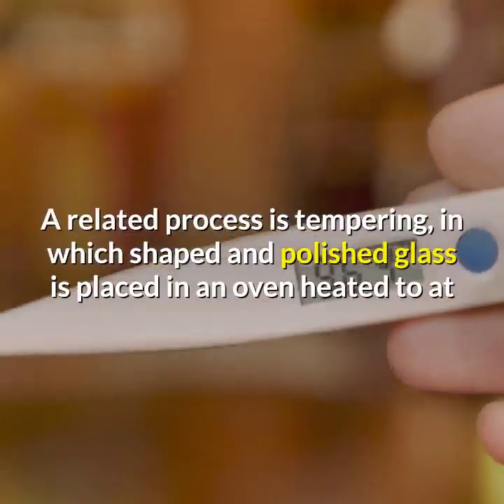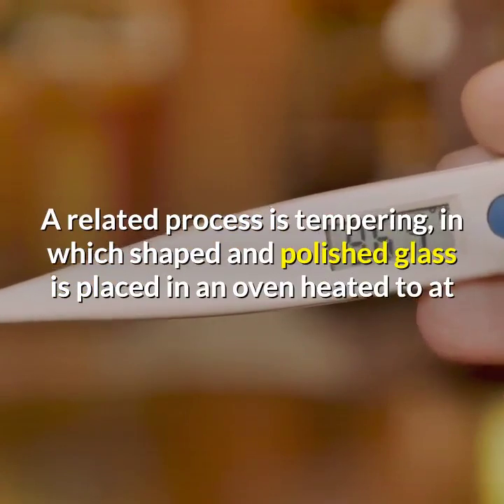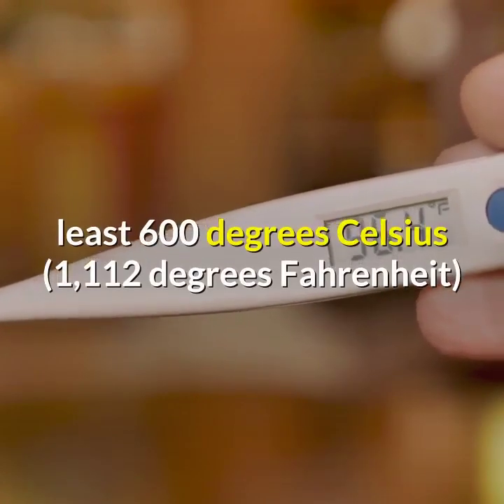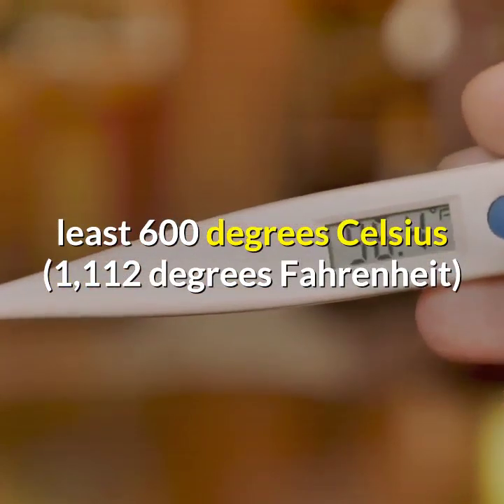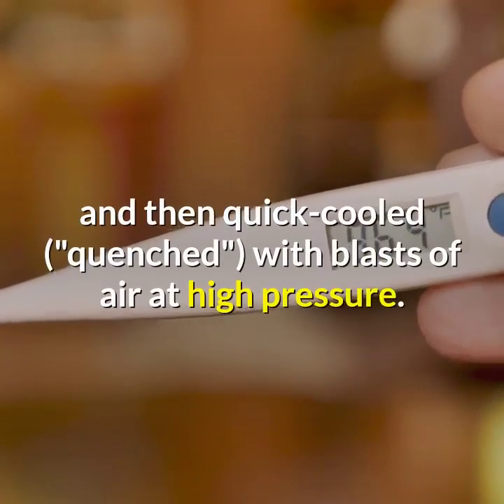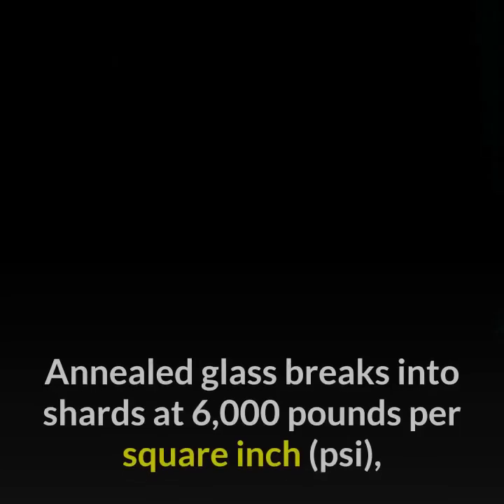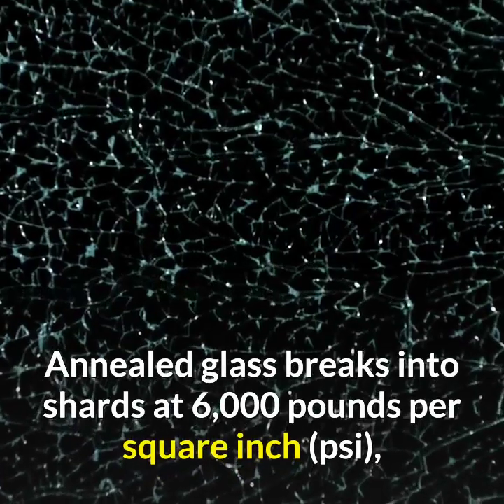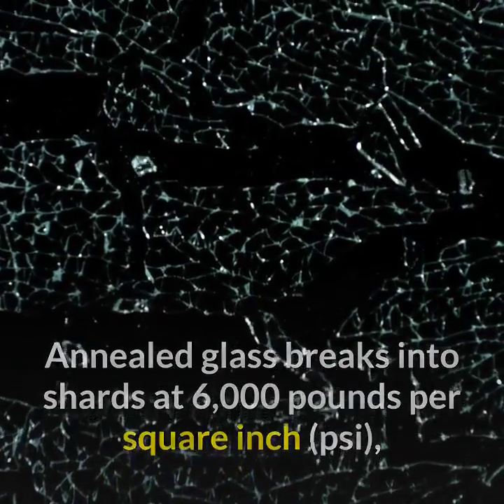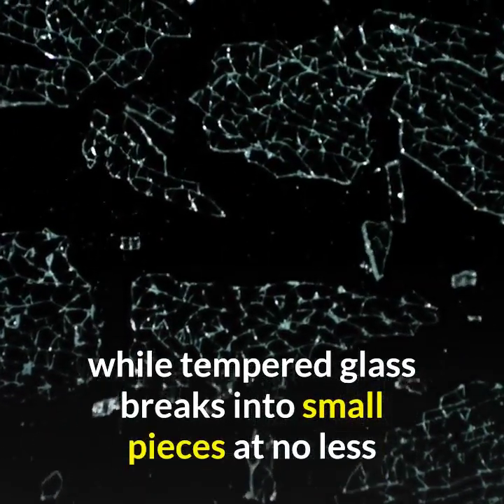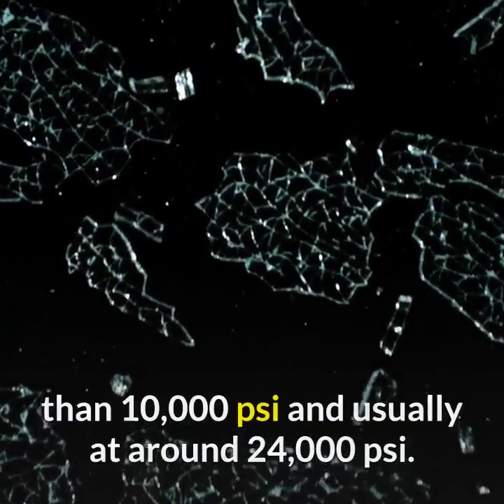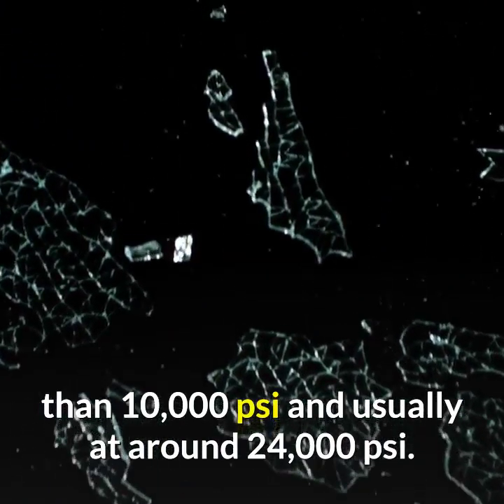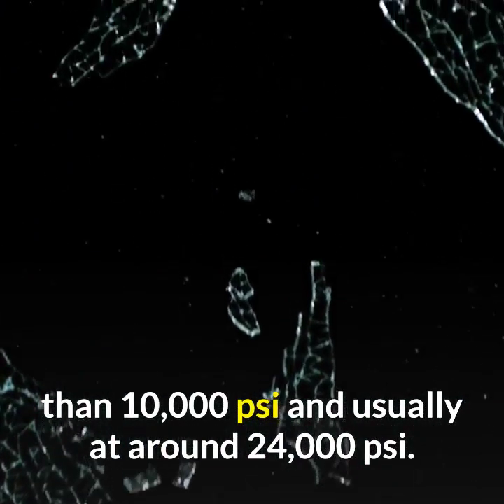A related process is tempering, in which shaped and polished glass is placed in an oven heated to at least 600 degrees Celsius (1112 degrees Fahrenheit) and then quick cooled, quenched with blasts of air at high pressure. Annealed glass breaks into shards at 6,000 pounds per square inch (psi), while tempered glass breaks into small pieces at no less than 10,000 psi and usually at around 24,000 psi.